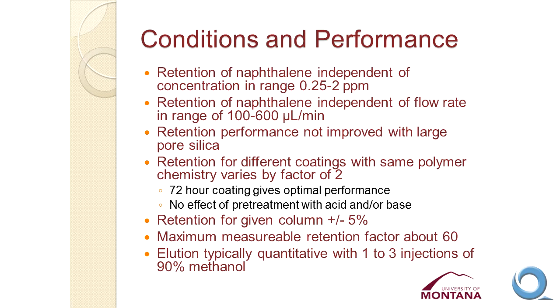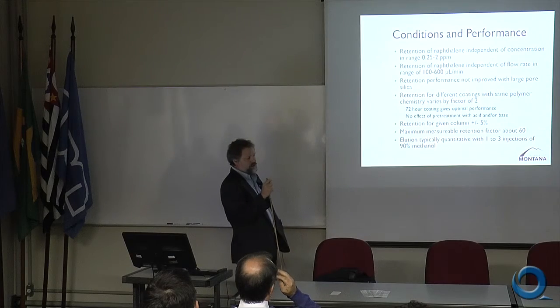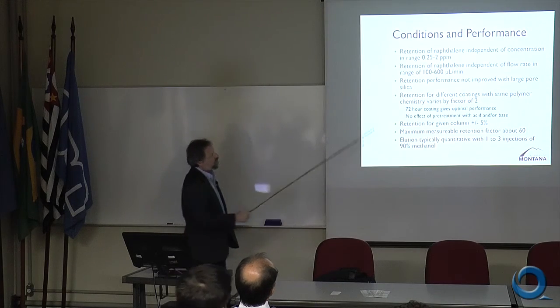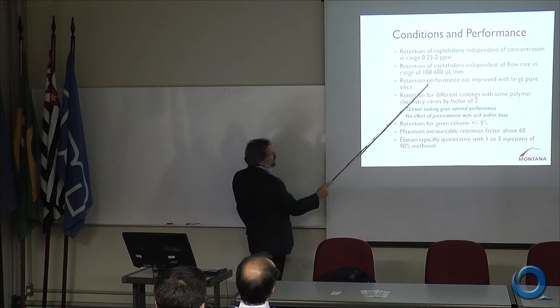We wanted to make sure that that front, which is not very sharp, as you noticed, was not being affected by the flow rate through the system. So we looked at flow rates between 100 and 600 microliters per minute. And again, we found no effect of the flow rate. So we did all of our experiments from that point on at 300 microliters per minute.